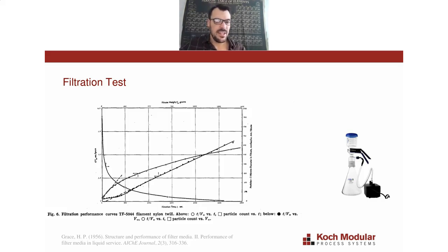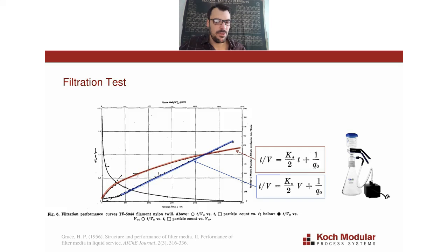That is, it tends to be the case that one of the two of those will be a straight line. In this case, T over V versus V, the blue curve, is the straight line. And that tells you something about the mode of filtration that's going on here. In the T over V versus T case, the red line case, if that one were the straight line, it would be indicative that as the cake builds up, the porosity of the cake is changing. It is shrinking with time.